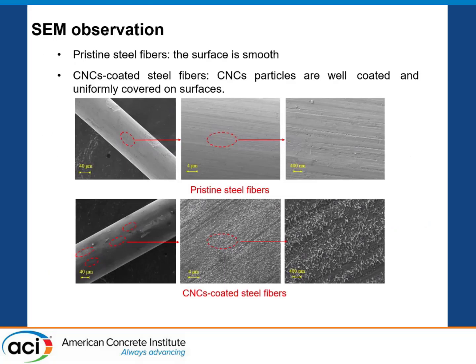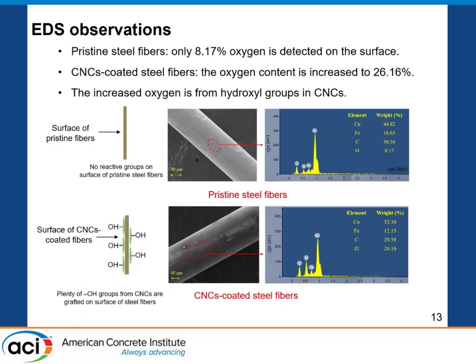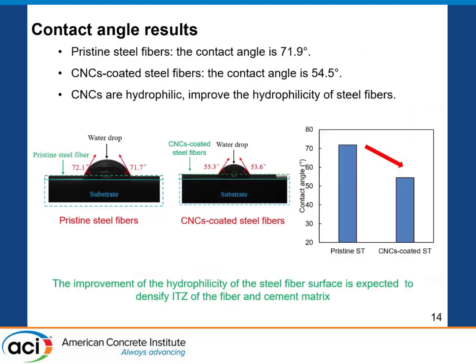From the SEM observations, you can see that the pristine steel fibers are pretty smooth. But when you have the CNC coated on the steel fibers, you will see the surface is much more roughened, and the CNC particles are very well coated and uniformly cover the surface of the steel fibers. From the EDS observations, we also observed that the CNC-coated steel fibers have much more oxygen content on the surface, which proves that the CNCs are very well coated on the surface of the steel fibers.